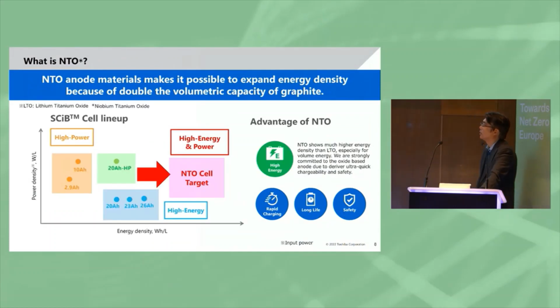So we selected the niobium titanium oxide anode. What is the NTO? NTO is one of the metal oxide anodes, and of course it can be used as an anode material like LTO. The main feature of the NTO is energy density. It has a very high energy density compared to the LTO, and the volume energy density is higher than that of the graphite anode, because it has the unique redox couple of niobium and titanium. So if the battery uses NTO as its anode, the energy density will be improved.